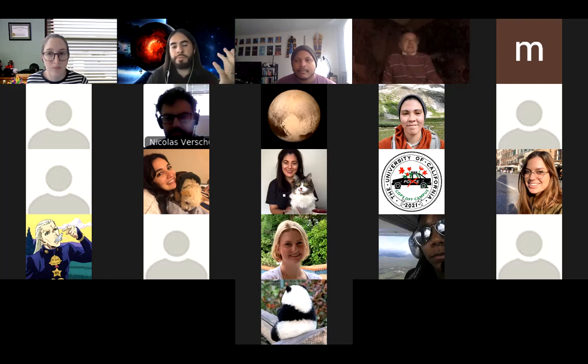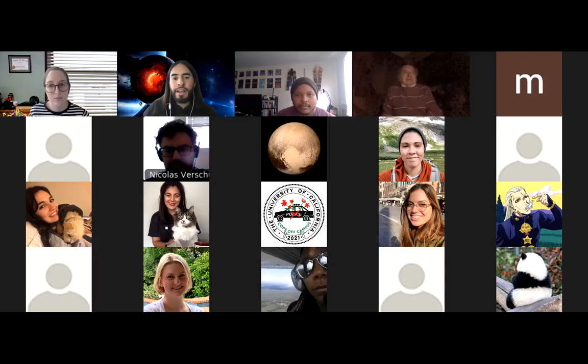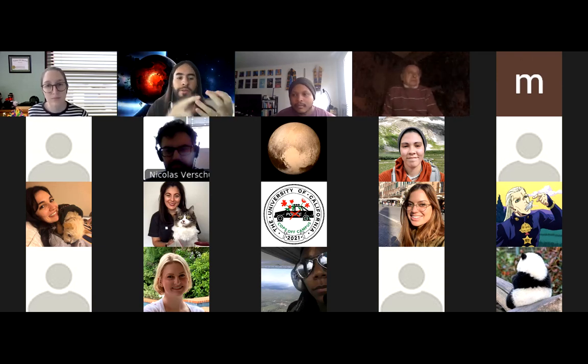Actually, yeah, that is what has been suggested by these experiments and simulations. Since there's a lot of silicates around in space, we think they're very likely to make the mantle of super Earths, but the temperature will be high enough, we think, that they can be molten. But in these molten states, these silicates like MgO, MgSiO3, silica, they can convect, and that convection could generate the magnetic field in these planets.